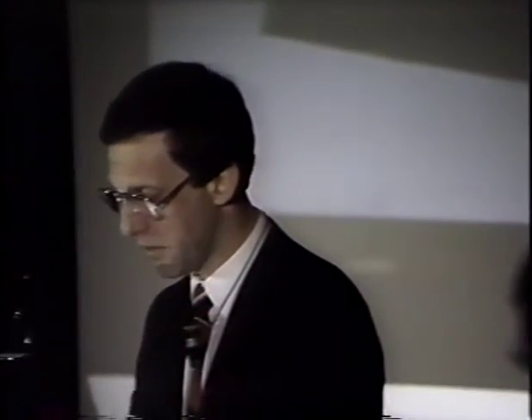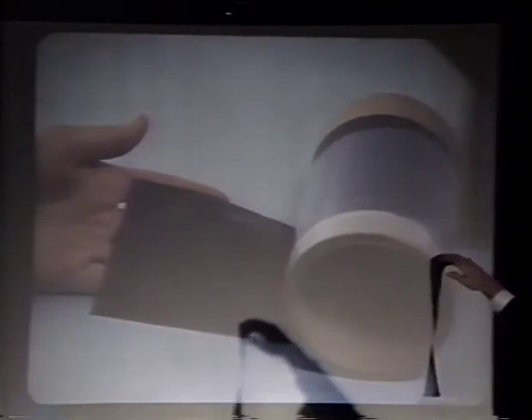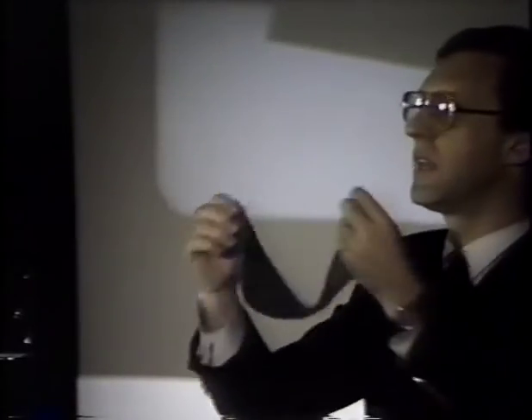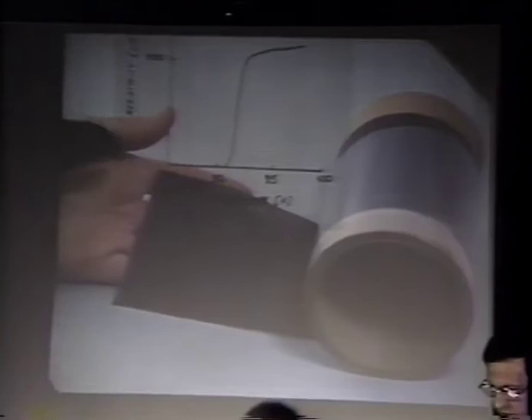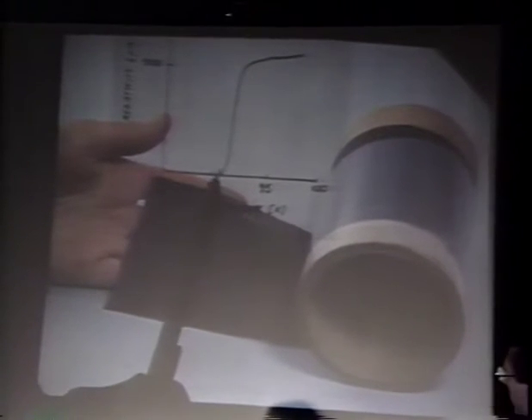One can make tape of this material. That's in the so-called green stage, where the material is not fired yet. That's one piece of that here, as you might see. You can shape it in any form you like. You can wind it up for a coil or whatever you like, then fire it, and you have a superconductor, which we have measured, and I just got the curve here. This foil indeed goes superconducting above 90 degrees.